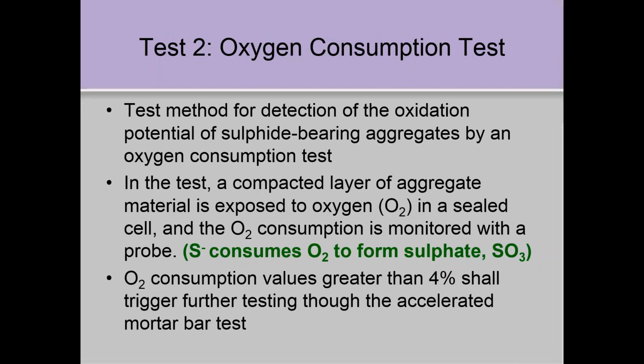The second one is it's a funny name, oxygen consumption test, because sulfides are reduced minerals. So they all want to oxidize, which is what pyrite does and causes the rust. It oxidizes. And pyrrhotite oxidizes more severely. So they measure the amount of oxygen that you put in a sealed container, the aggregate, and measure the amount of oxygen that's consumed by the oxidation process. And if it's above a certain amount, then you do a mortar bar test.